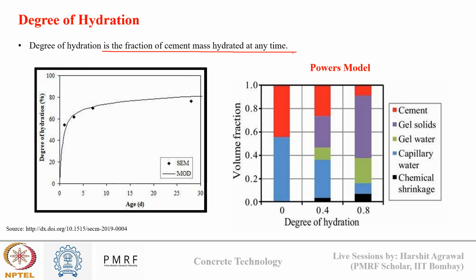It continues for a long period. That's why we can see in the first figure how hydration, after the initial steep rise, continues to increase steadily at a steady pace till 28 days. Okay, so this is the degree of hydration, the amount of water that is consumed by the system. Initially it is very high, and then it slows down, and then hydration slowly continues.